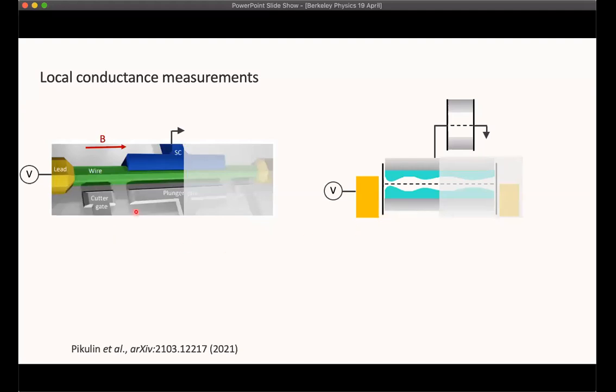And so I'll begin with this schematic of our wires that we measure and show you that all of these spectra that I've showed you so far are local conductance measurements of one end of the wire. So we're applying a voltage on this normal lead relative to our superconductor, actually, that we've grounded, and we're measuring tunneling through a barrier that's defined right about here. So this is telling us about the physics going on this end of the wire.